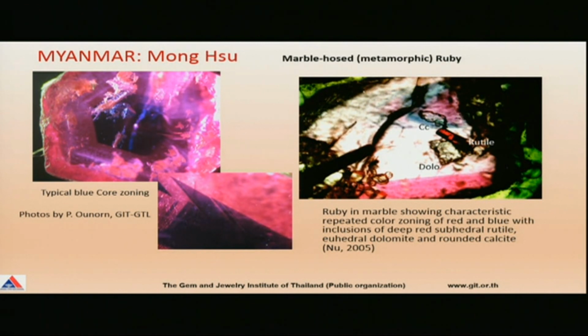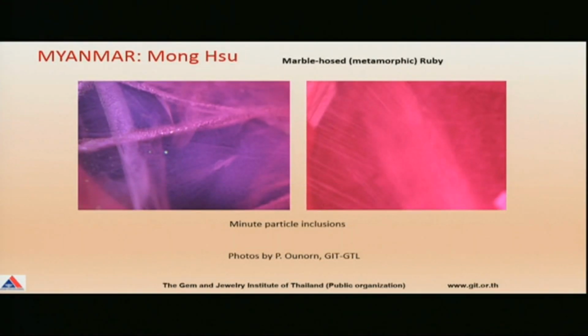And also, you can see this is a big piece. You can see alternating zones, red to blue, colorless to blue, and some inclusions like this dark, deep red rutile, rhombic dolomite, and also some corroded calcite in this stone. Also, another typical feature of the untreated marble Mong Hsu is a little bit of minute cloudy type inclusion that is found here. But when it's treated, it becomes clear. It gets rid of this minute stuff.